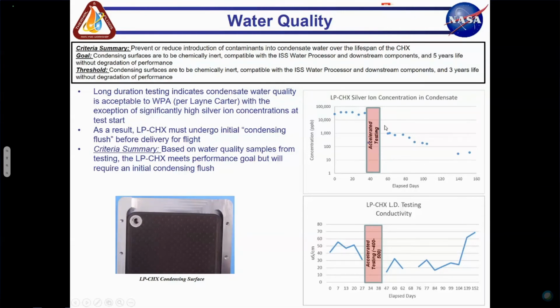It's roughly about 30 to 40,000 ppb when we start testing before it drops down. So the picture on the right-hand side is the elapsed days, and the concentration of that silver ion is on the left end of that axis. And you can see how it drops down over time. We did do a period of accelerated testing where we just flowed water, about 200 gallons, over the surface. So that's one of the reasons why there's a big drop in between days like 40 and 50 there.